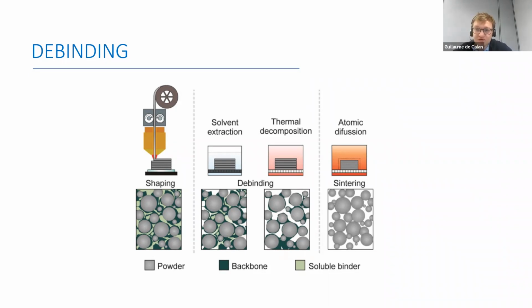This is usually, if you have cracks, you'll usually see them already in the solvent extraction, and if not, you'll see them afterwards in thermal decomposition. But usually you see them already during solvent extraction. And if you have cracks, that usually means you haven't made a complete debinding. And you still have too much binder in the part when you remove it.